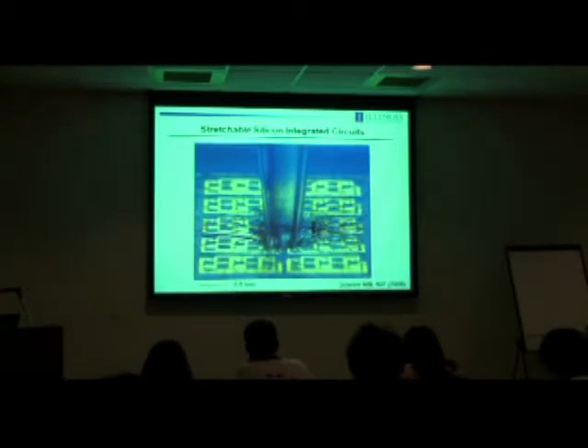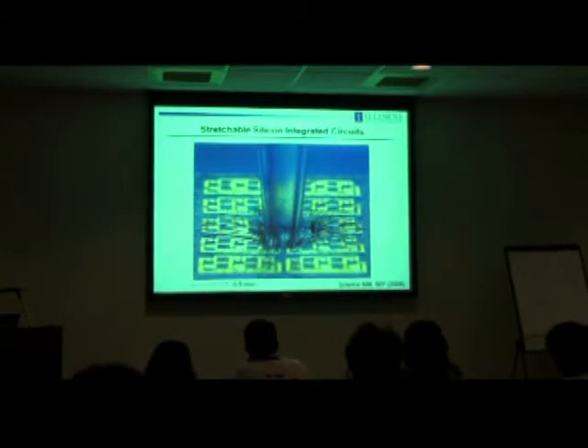Okay, so these circuits are not only stretchable, but they're soft, you know, at a mechanical level. And this was a nice image that people in our Beckman Institute took for us. We dropped off the circuit, and they came up with this nice posing, which I think is aesthetically appealing, but also kind of demonstrates the physics a little bit. So this is one of these wavy circuits on rubber, and then into the center of this thing, the photographer plunged a glass pipette to induce some local deformation here. And what you can see is these wave structures move into form to accommodate this kind of local strain.